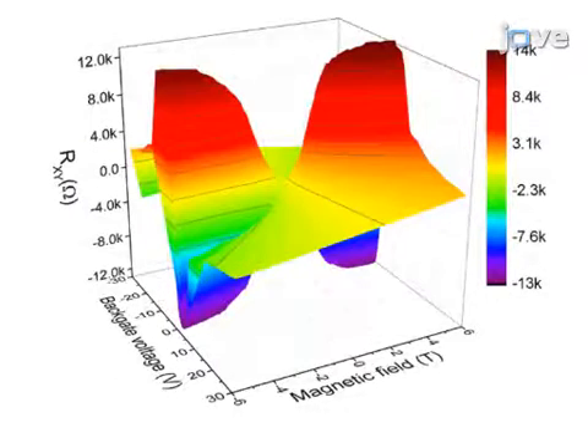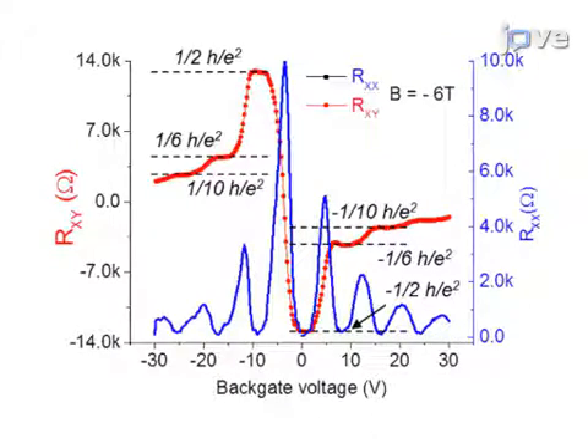The experimental parameters included exposing the device to magnetic fields as high as 12 Tesla, temperatures as low as 0.3 Kelvin, and gate voltages as high as 30 volts. The plateaus of the measured Hall resistance correspond to Landau level filling. This is a model example of the quantum Hall effect. At 6 Tesla, Hall resistance and longitudinal resistance were examined as functions of back gate voltage to describe the quantum Hall effect on graphene.